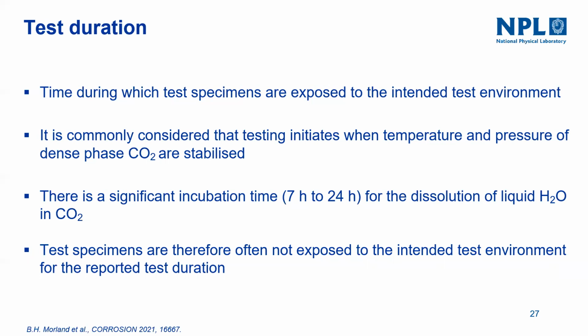So normally what happens is once we add the liquid water, to go into the soluble state, it takes like 7 to 24 hours. It also depends on different experimental conditions. So technically, the test specimens are not often exposed to the intended test environment for the whole duration of the testing.